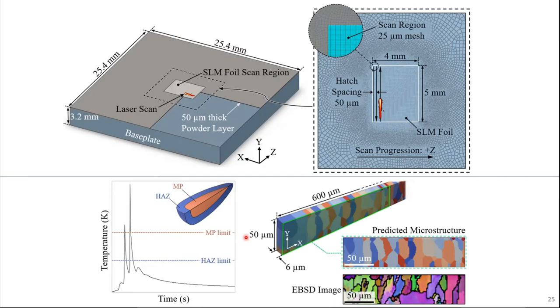Master's dissertations. So just to give you an idea, this is our SLM finite element model. Again, I ran this with aluminium 1100 as well as stainless steel, just to get the melt pool and heat affected zone limits, from which we can then run the dynamic KMC and get these grain structures. So we basically took these foil structures. The thickness you're seeing over here, 50 micron, is basically in the Y direction. This top face, which you're seeing over here, basically runs along the top face over here. And we get these grains and we compare them.